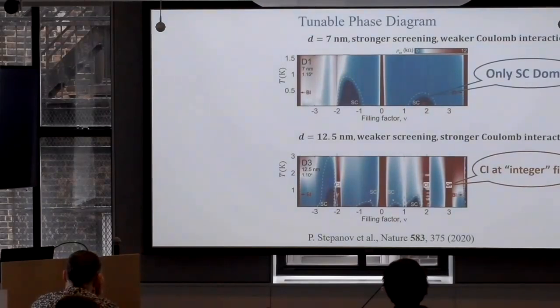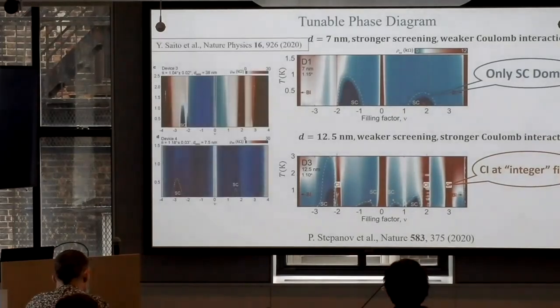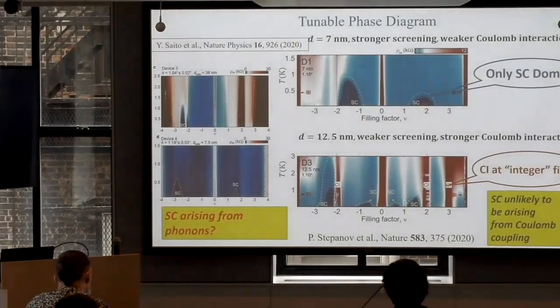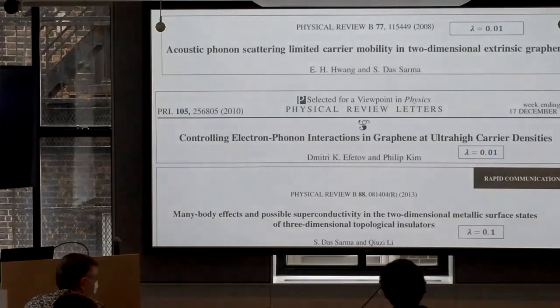Okay, so this is what I was telling you, I just gave you the punchline. So at 7 nanometers, stronger screening, only superconductivity survives, okay? And then when you go to 12.5 nanometers, weaker screening, correlated insulator phases come out, okay? So this is some evidence that it cannot be regular electron-electron. So these are the papers that I read from the abstract already.